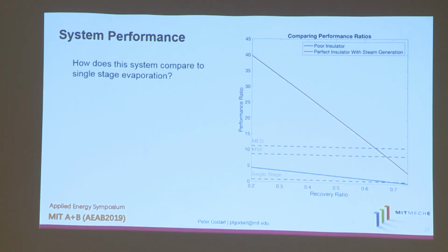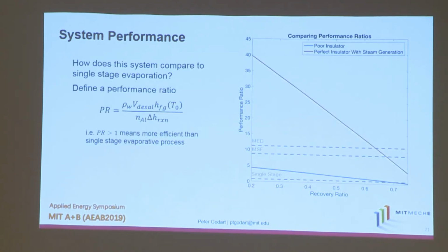Very small amount. We can compare this type of system to just simply boiling off the water by defining a standard performance ratio, which is just the ratio of the latent heat of the water that we've desalinated to the amount of thermal energy we've put into that system by the change in enthalpy from the product to the reactants of that aluminum water reaction. And we show that in the upper bound case, we have a performance ratio of 40 for low recovery ratios, which means that we can desalinate 40 times more water than just simply boiling off the water in one stage alone.